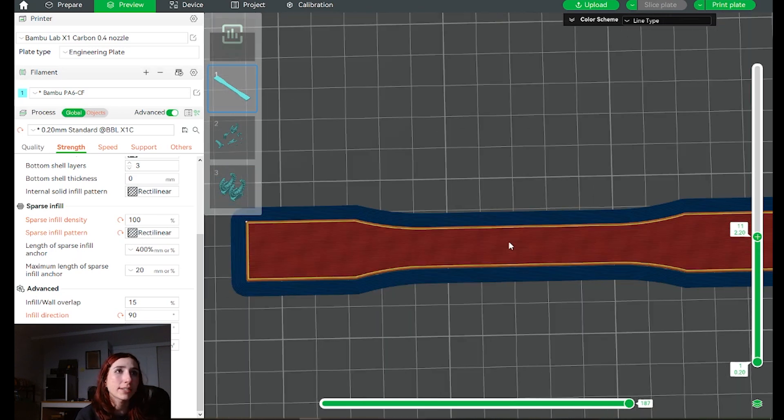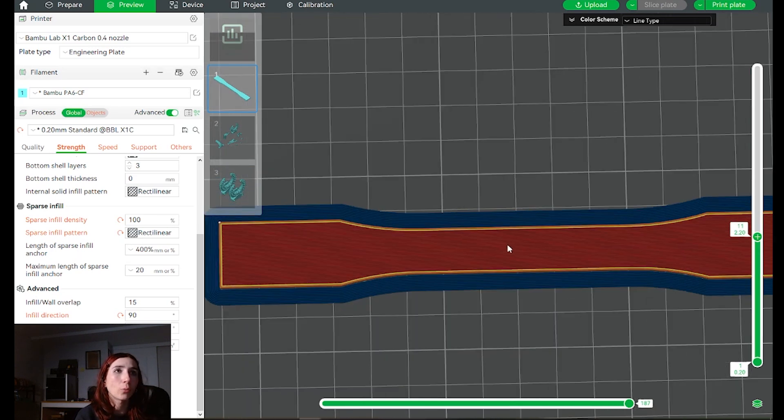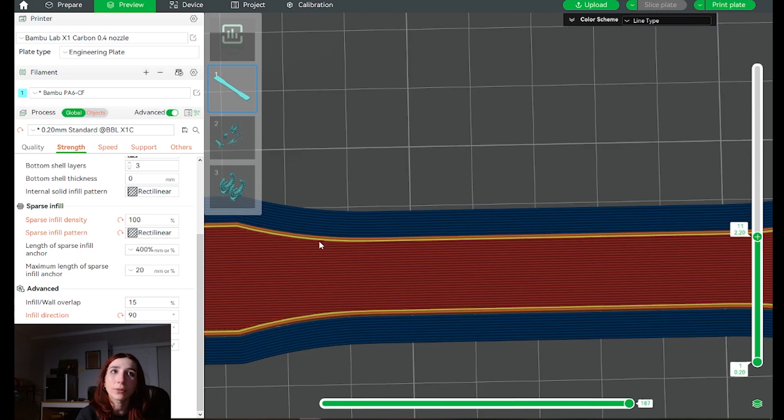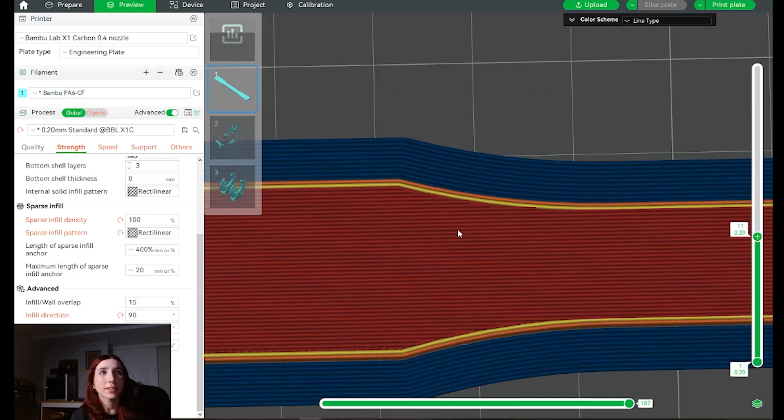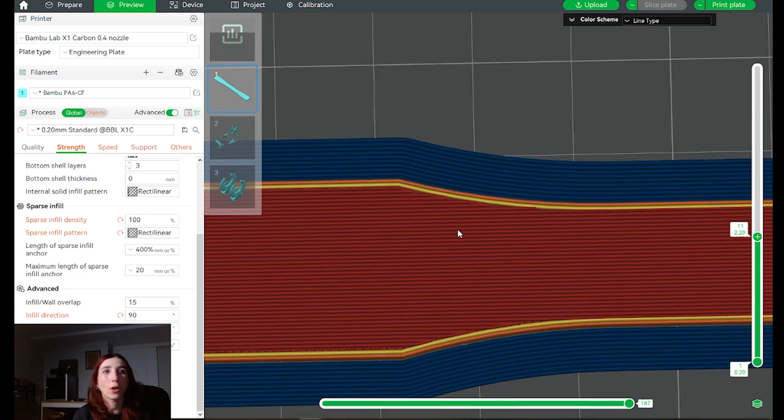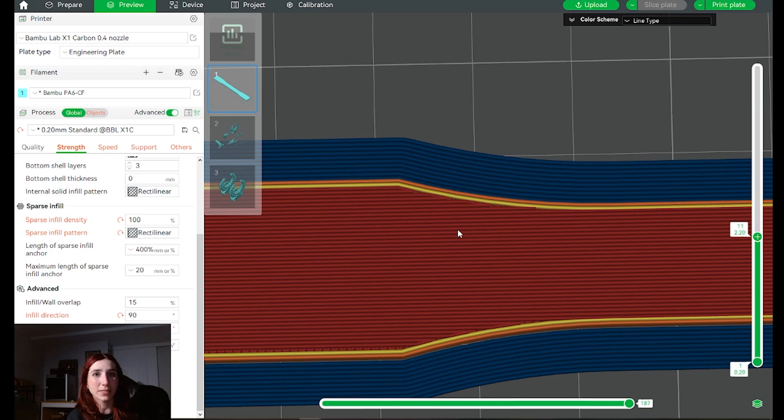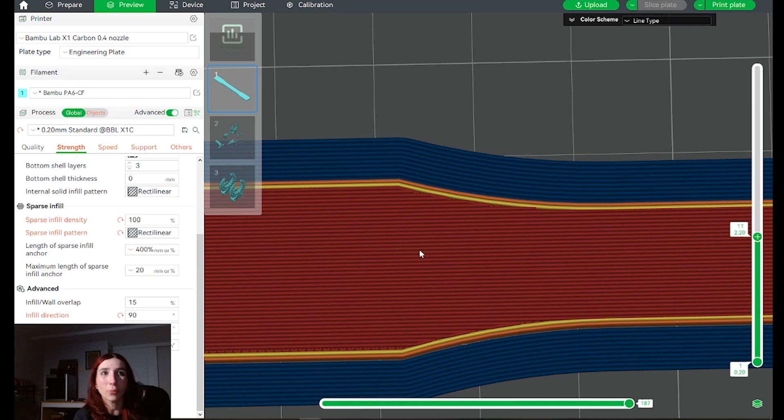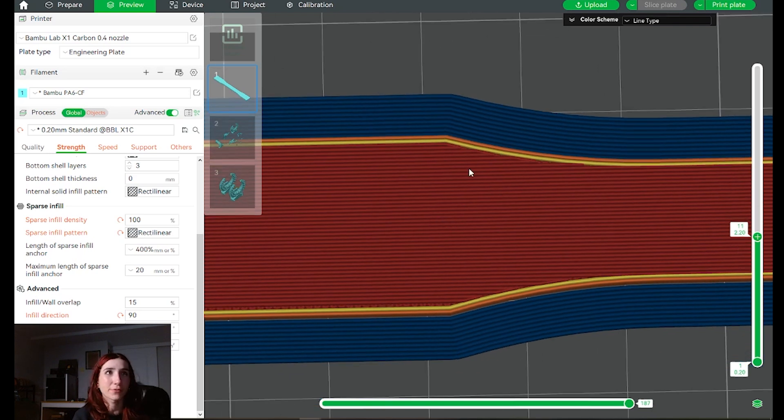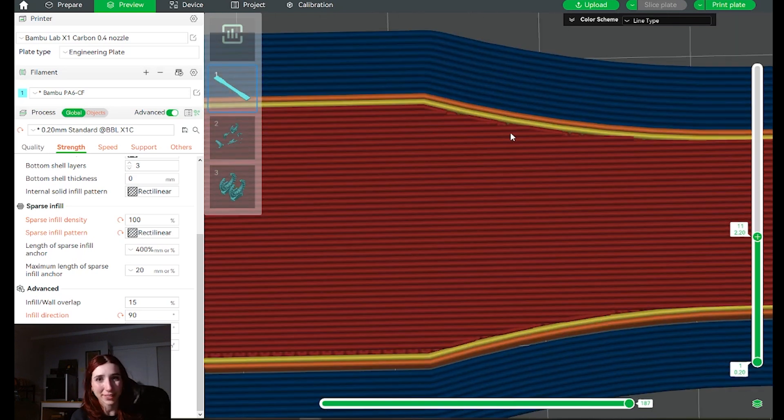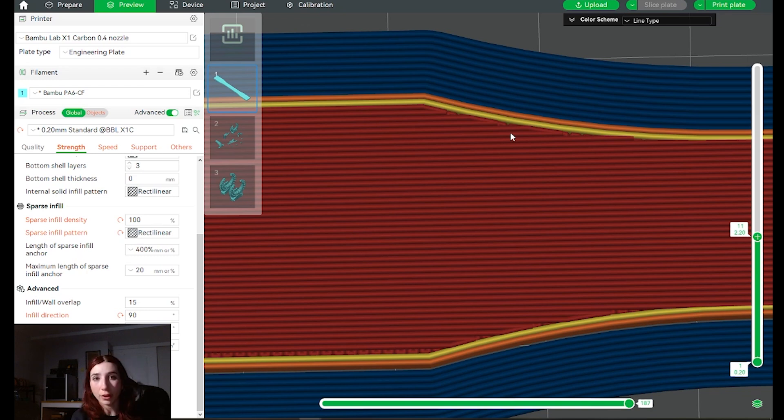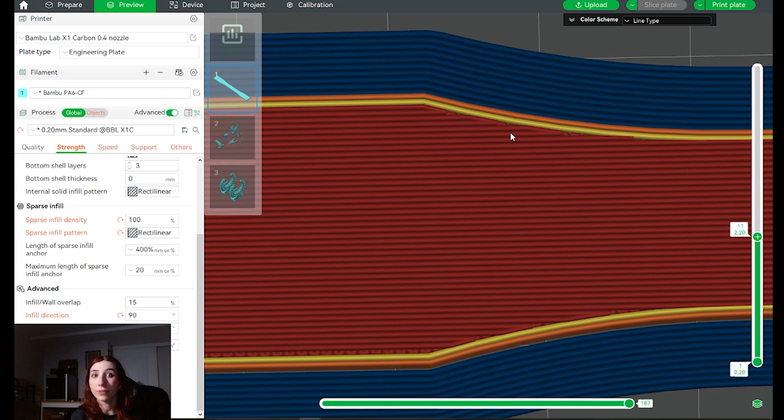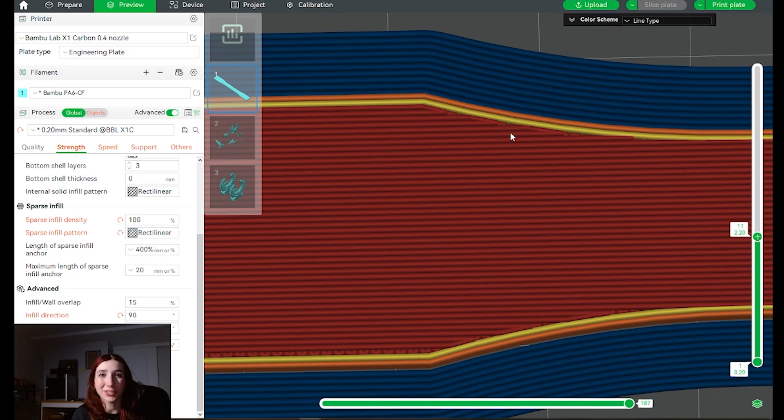Or slice it in a way where we don't get these voids? Slicing it in a way where we minimize voids would not always be possible, specifically if we want to get results for orientations that do cause these major voids. Whether we go in and iron each layer while we're printing, gap fill after every layer with a void-focused toolpath, or we print overlapping beads, something needs to change here for these testing standards.